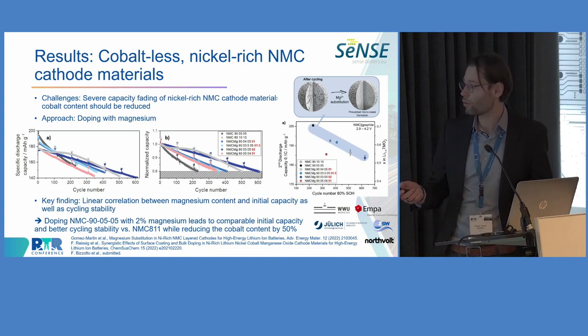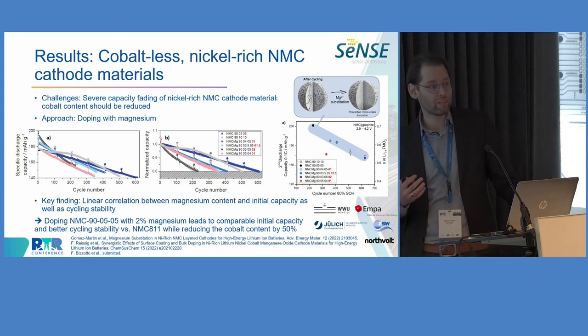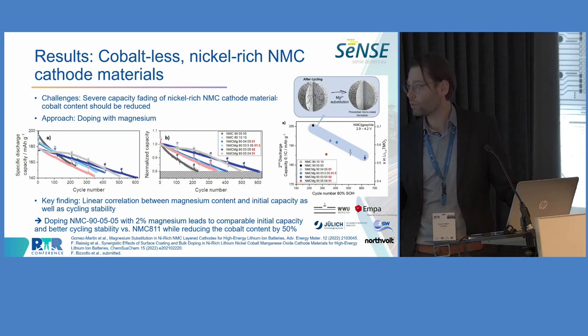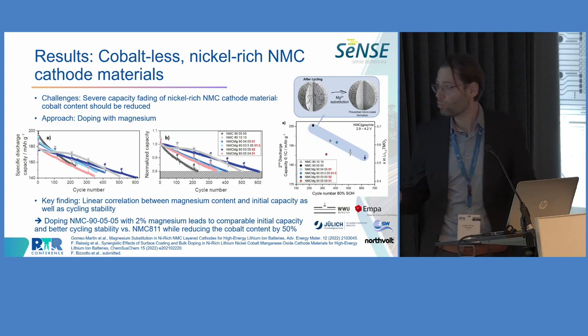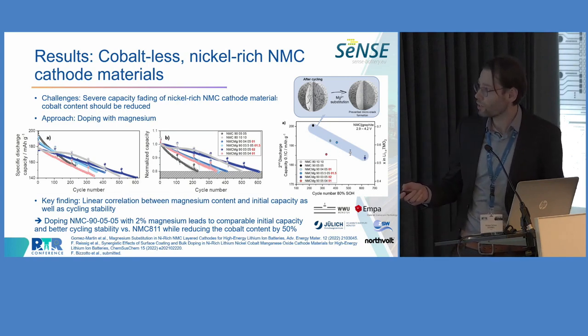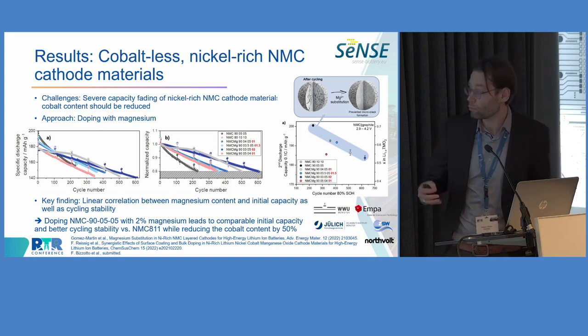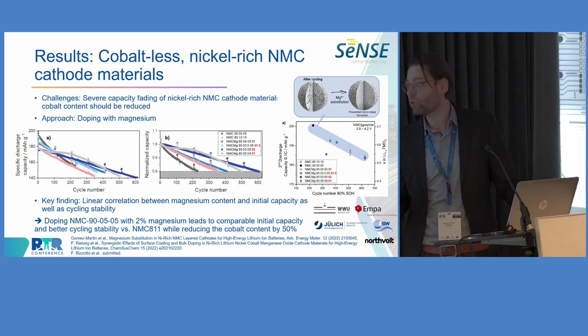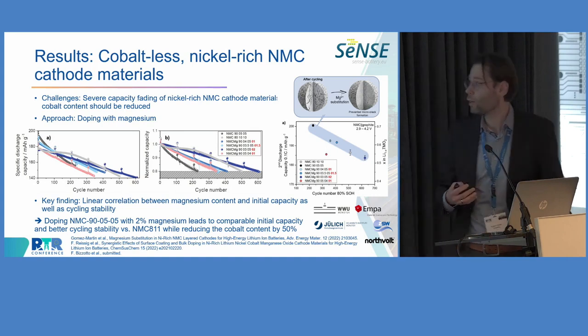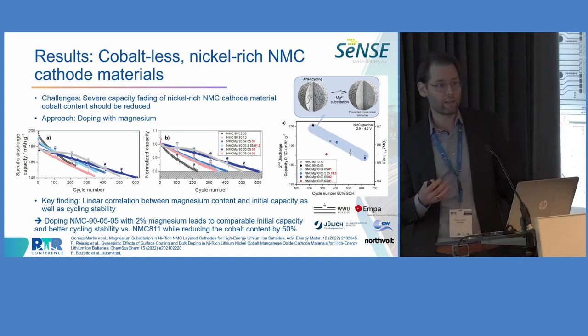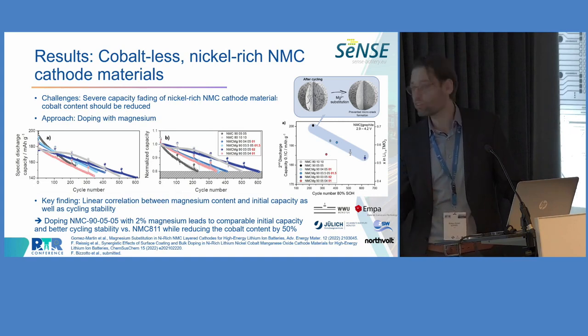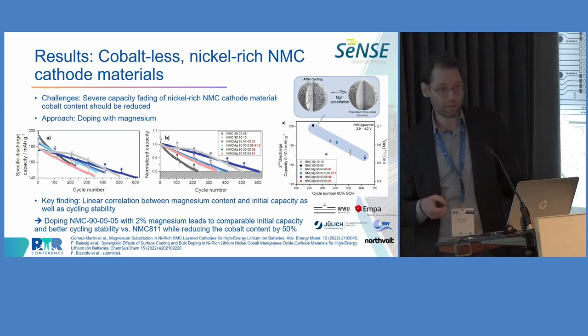And in this example that was published last year in Advanced Energy Materials, we tried to substitute some of the cobalt by magnesium. And what is quite interesting, when you put 2% magnesium inside the material, you end up with a material that has a comparable or even slightly better cycling stability here in dark blue if you compare to NMC 811, with similar initial capacity. While we are reducing the cobalt content by 50%, which is really important, right? And at the moment we are upscaling NMC materials for the second generation prototype. So this is the work of our partner ZSW that is doing the upscaling.